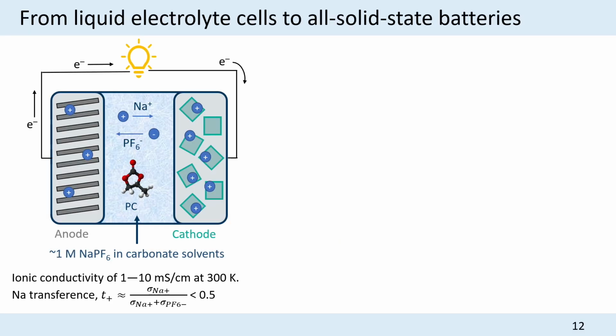So the motivation here is that our current state-of-the-art rechargeable batteries typically have a liquid electrolyte, and this is composed of, in our case, a sodium hexafluorophosphate salt, 1 molar concentration, dissolved in a carbonate solvent. The problem with these types of electrolytes is that your carbonate solvent is flammable and it has a limited electrochemical stability, so it decomposes at high voltage.